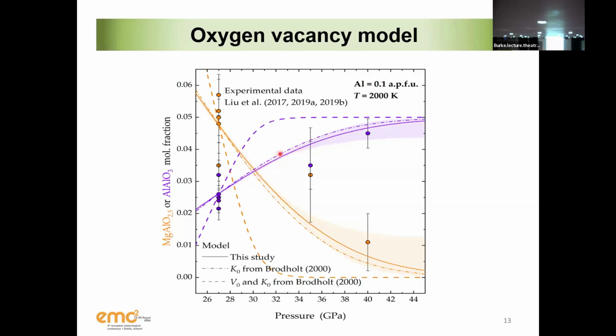But what I want to show you is simply that this is our model today, which fits the few very large uncertain data we have. This model, with this dashed line, is based on the EOS parameters that Brodholt reported in his compilation. You can see that one was really missing, especially this middle point. In the old days, when you had this major difference between the two mechanisms in terms of compressibility, you would have expected the oxygen vacancy mechanism to go down much faster than it looks like it happens, okay?